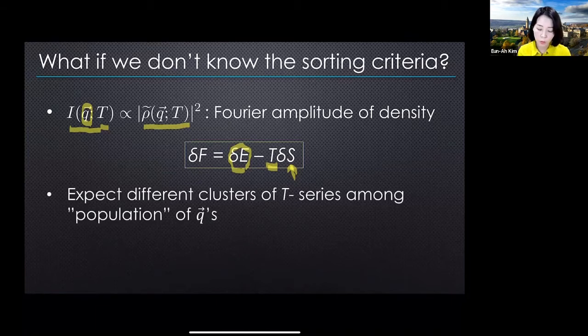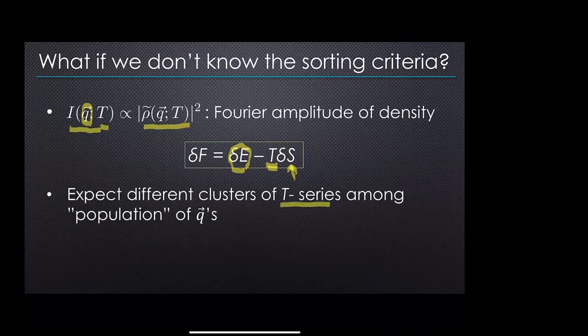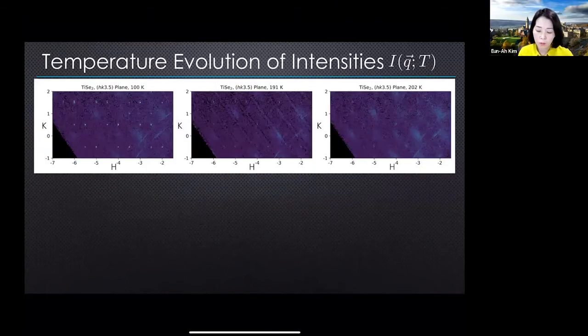So we had the idea that we can anticipate qualitatively different types of temperature dependence, different types of temperature series among the population of reciprocal space points. So here's an example of how that kind of evolution looks. This is titanium diselenide data that we used to develop the tool. It's a material that is well known to develop charge density waves. And you can see here, if you have chosen the right plane, this is the half plane where the charge density wave peaks exist. These superlattice peaks become fainter, and they sort of disappear as you go up in temperature, whereas this background is more or less temperature independent. So that was the idea. That was a simple idea.